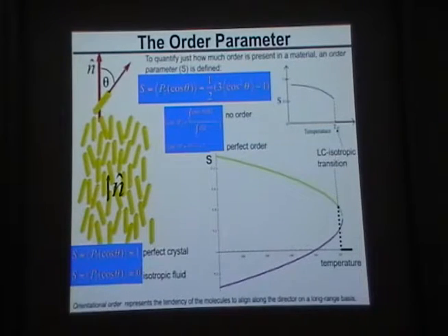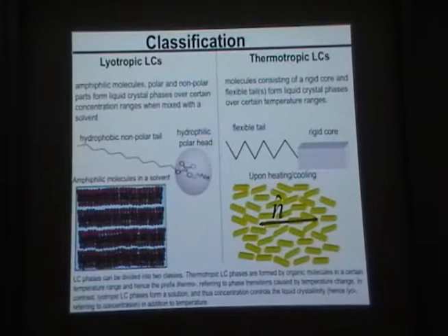Usually it's smaller than that. At room temperature of many liquid crystals it could be, say, 0.7, 0.6. And then when you would heat your liquid crystal material further, at some moment you would have discontinuous transition to the isotropic state, and that's when the order parameter value discontinuously changes to 0, right? Because in isotropic fluids, the order parameter is equal to 0.